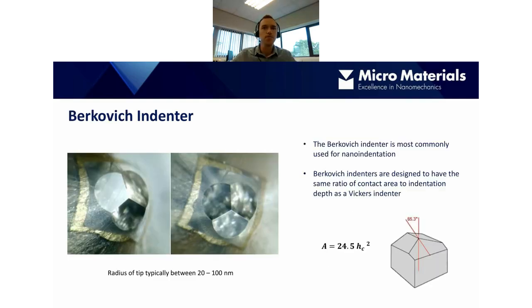So the Berkovich indenter, as I say, is most commonly used for nanoindentation. It was designed from the outset to have the same ratio of contact area to indentation depth as a Vickers indenter. So the geometry of the indenter, the face angles, was designed to have this equal ratio with the Vickers indenter. Incidentally, it was named after the Russian scientist that devised the geometry, who was called Berkovich. The reason it was a three-sided rather than a four-sided pyramid is because it's simply easier to grind the diamond to a fine point with three sides compared to four sides.